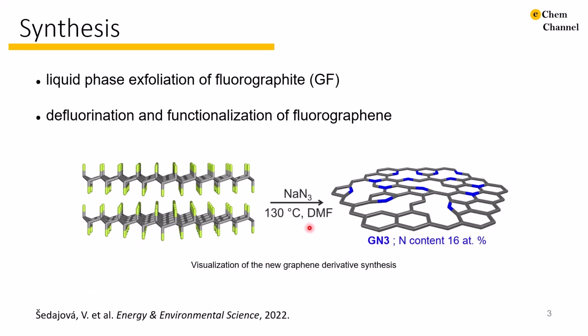phase, and then we use sodium azide as a nitrogen source. The azide anion initiated the reaction by nucleophilic attack on carbon radical defects, leading to nitrogen release and fluorine elimination. As the final product, we get the nitrogen-doped graphene, denoted as GN3, with superdoping of 16 atomic percent of nitrogen.